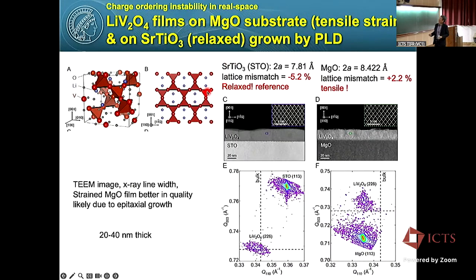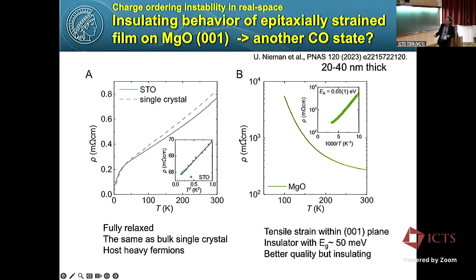So I strained them by using a thin film, and we prepared two substrates for the LiV2O4 thin film. Strontium titanate matches well, and the film just relaxed and shows the same lattice constant as bulk LiV2O4. But if I put it on magnesium oxide, the mismatch is only 2%, tensile strain. And they do grow epitaxially. And we measured the resistivity, and the relaxed film with the same lattice constant as the bulk crystal shows heavy Fermion behavior, no doubt.